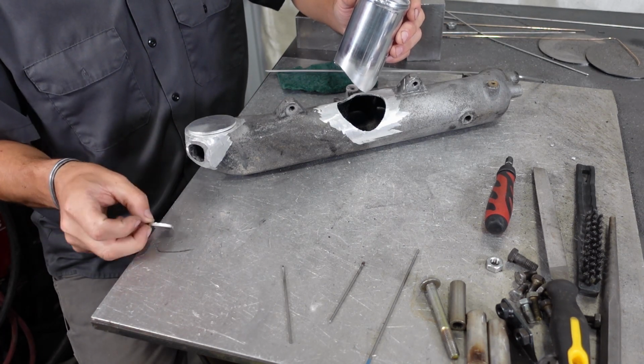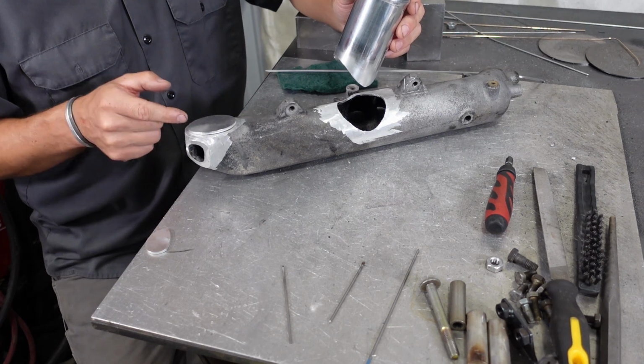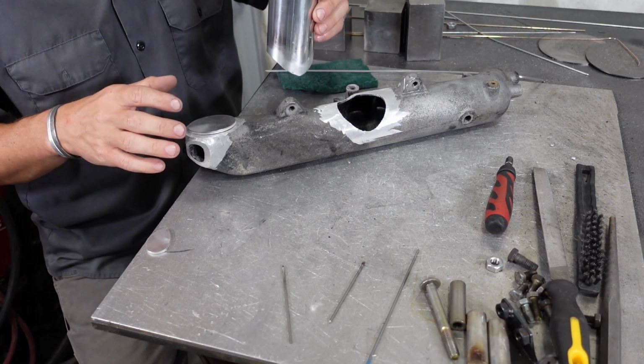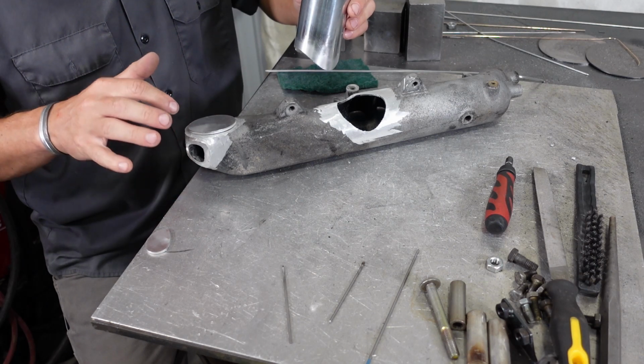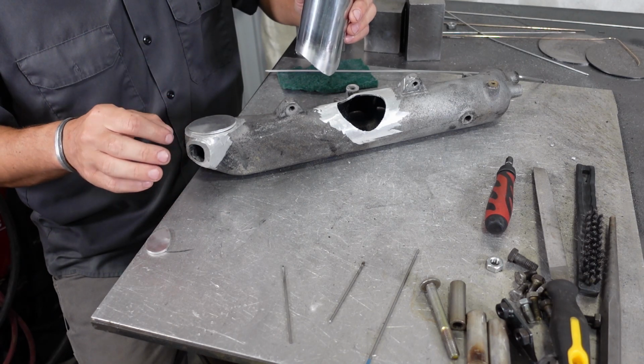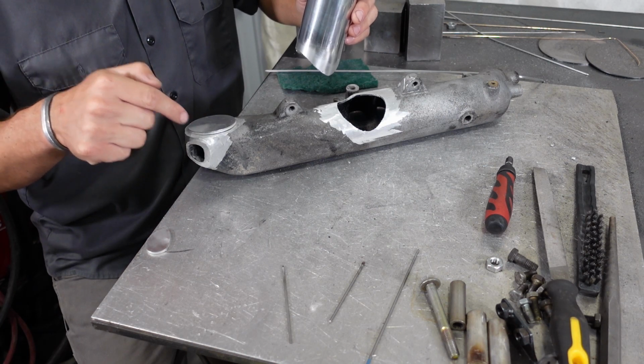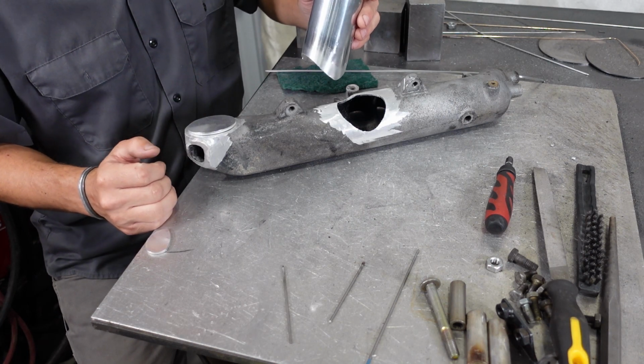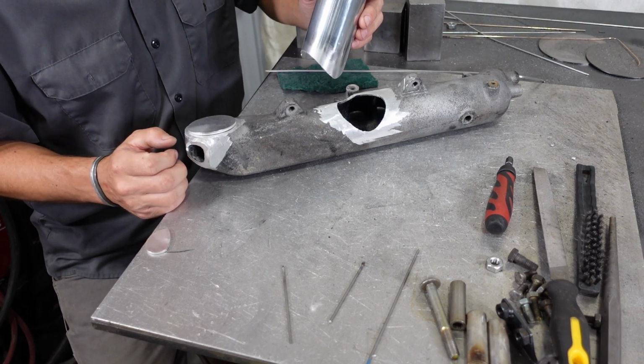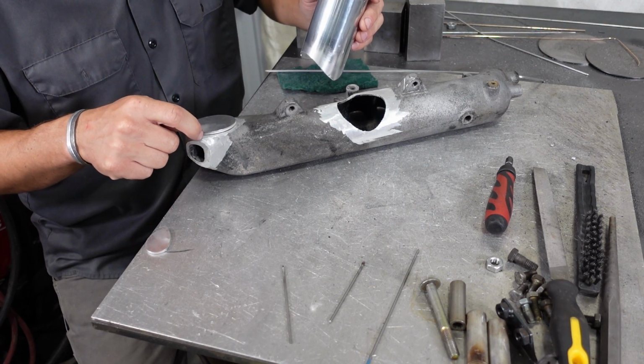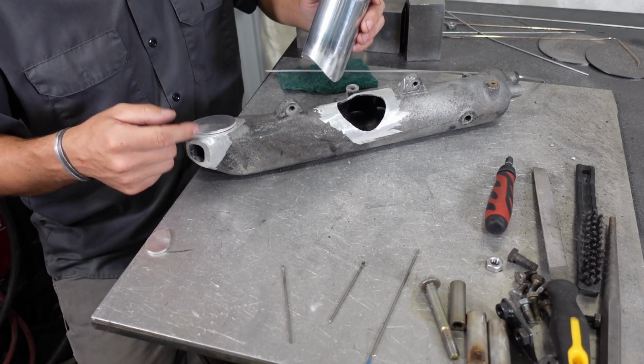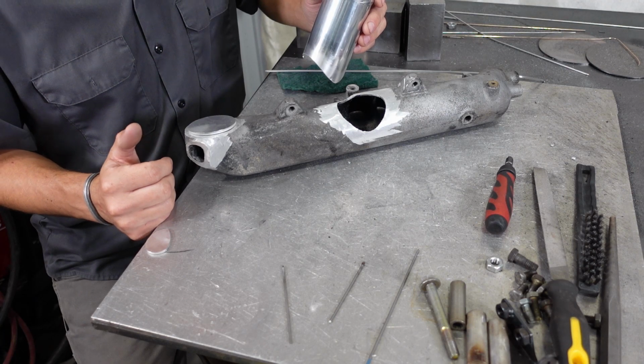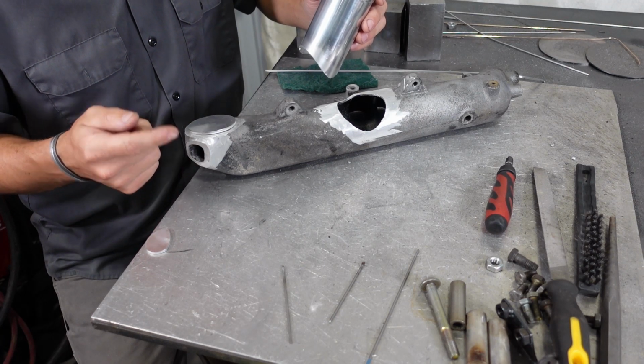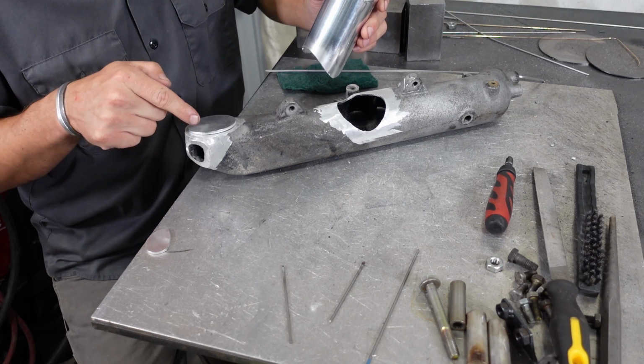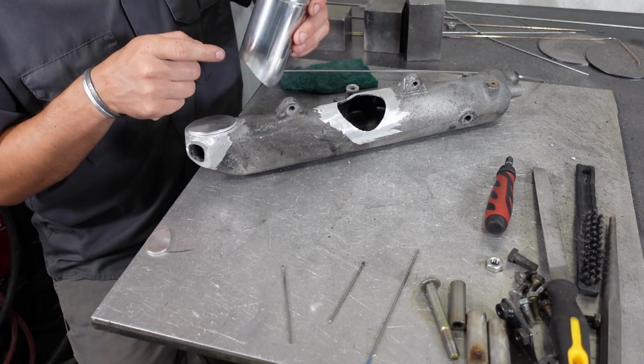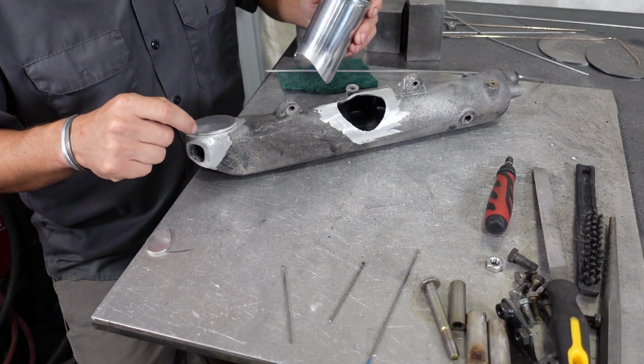And the reason for that is if I add the bigger piece first, that's just more heat sink, because when you weld cast, the biggest thing is you want to keep as much heat out of the cast as possible. Or in other words, you want minimum heat input in the cast. So we don't want our welder putting a lot of cleaning action on the cast, because it's going to continue to draw impurities out, which is going to increase the likelihood for porosity, which leads to leaks and cracks. So you want to focus your heat on the laser cut parts and the tubing. Minimize how much heat you're putting into the cast.